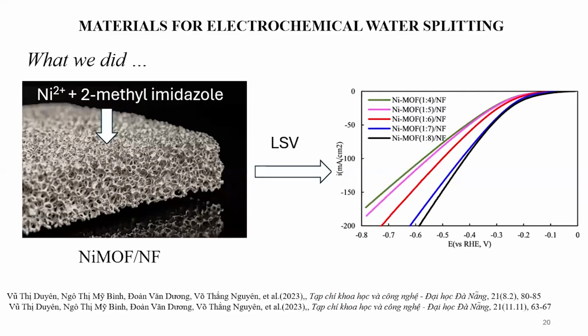Finally, our recent research is regarding electrochemical water splitting to release hydrogen. In this research area, we are now interested in the formation of MOF from nickel. So up to now, there are two materials that we are interested in. The first one is the formation of nickel MOF on the surface of nickel foam. And we use 2-methylimidazole as the organic ligand, and we tested the hydrogen evolution reaction. And this is the result we show, which I'll talk about later.